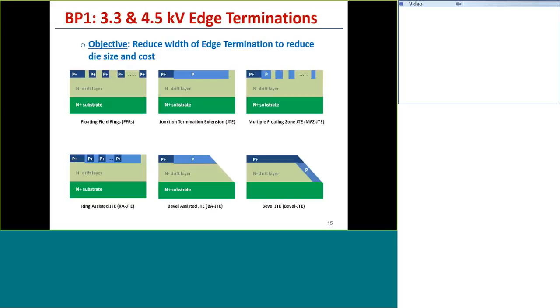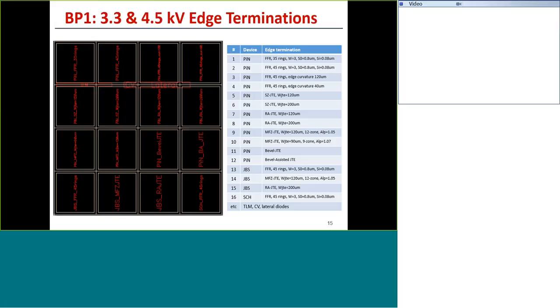Turning to the other project that we did in BP1, these are edge terminations of reduced size for 3.3 kV and 4.5 kV devices, and we proposed numerous designs: FFRs, JTE, MFZJTE, ring-assisted JTE, and then we have been creating this unique bevel termination at NC State with great success, so we also proposed those. A mask design was done to fabricate these devices with various PIN diodes and even some JBS FETs and Schottky diodes.